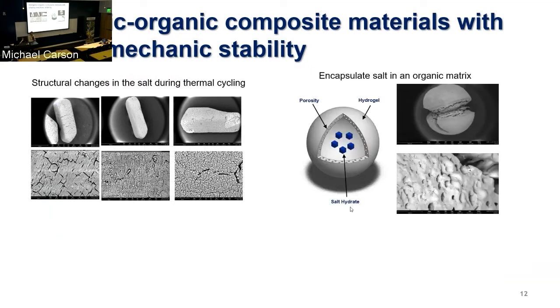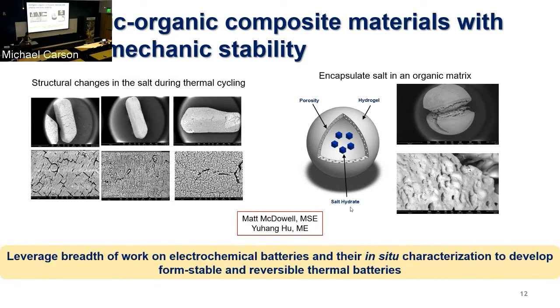So we're looking at stabilizing these materials by developing organic-inorganic composites where the salts are held in place by an organic matrix which acts as a scaffold. This is work that we're doing with Professor Yuhang Hu's group here at Georgia Tech. They develop a lot of hydrogel materials primarily for mechanics and materials applications, and these gels have been shown to be self-healable. So we want to now use these self-healable gels in this type of system so that even if there is cracking as you cycle the material, the gel can heal itself.